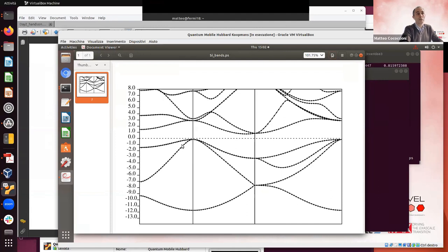The reason is that this material is covalent. So using atomic instead of orthogonalized atomic means that you're counting electrons twice in the interstitials, because you're not orthogonalizing the atomic wave functions between atoms. On the same atom the atomic wave functions are orthogonal because of their angular part, but between atoms there's no obvious orthogonalization.